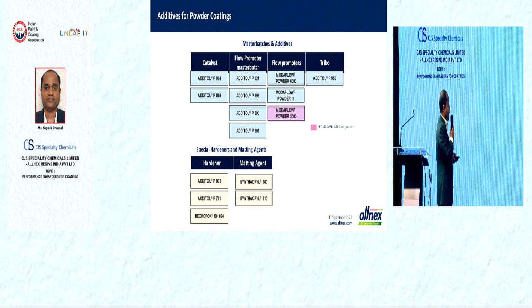This Tribo Additol P950 is generally recommended to improve the charge of the powder coating. Generally in the powder coating process, there is charging for the electrostatic application, and to improve the charge of the powder paints, this tribo additive works very well.